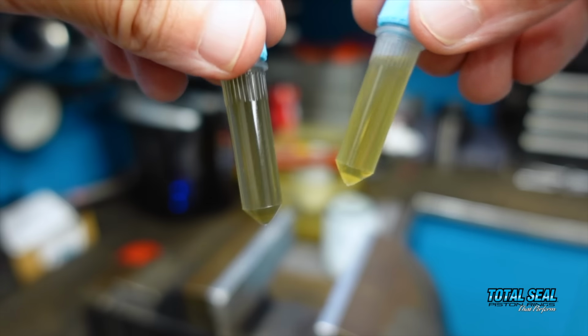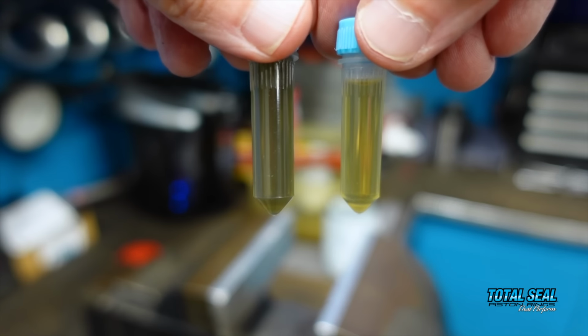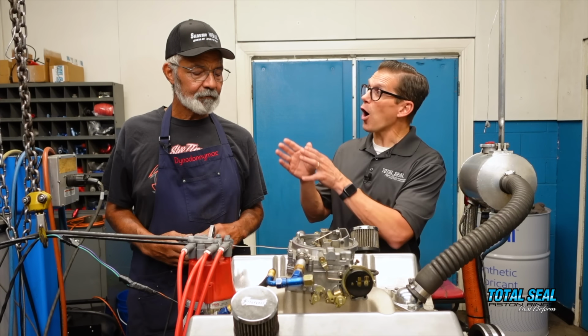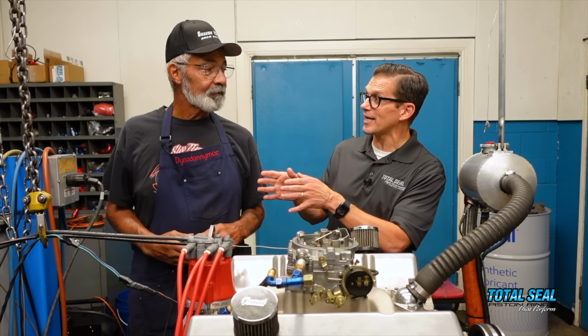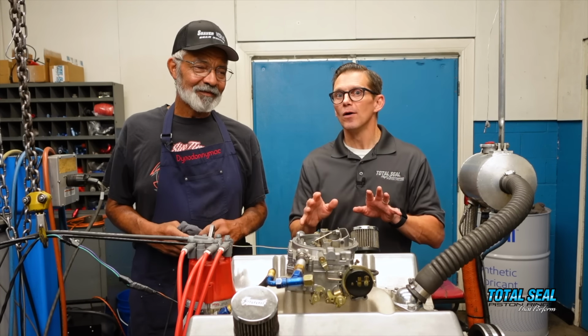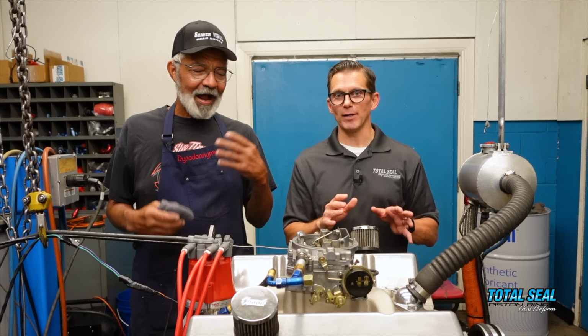To maintain that 190 degree water temperature with the 16th ring, it made over 300 degrees oil temperature. I think I saw 312, 313, something like that. That gets to a scary point right there. Right. And we were only about 290, 280 something with the 9 millimeter ring.